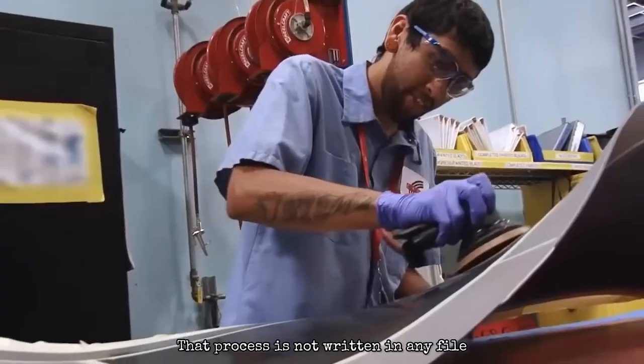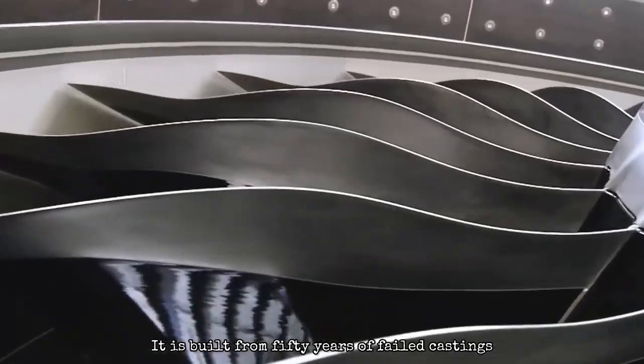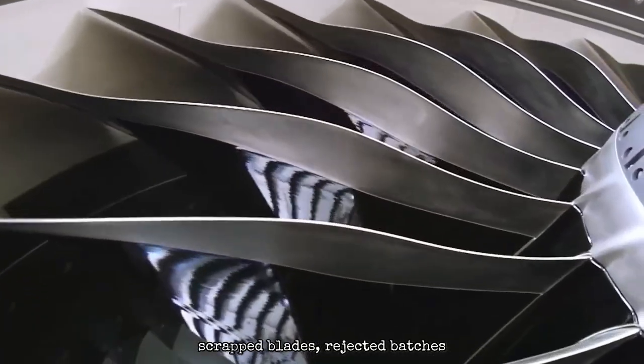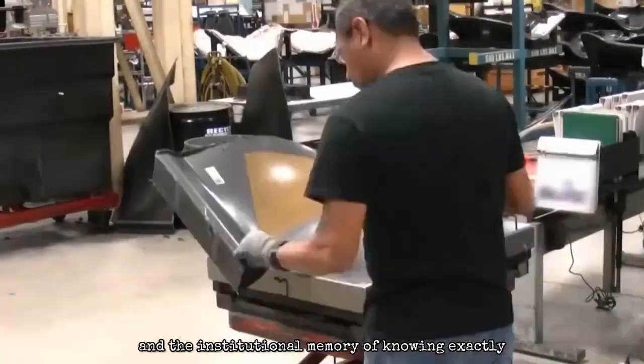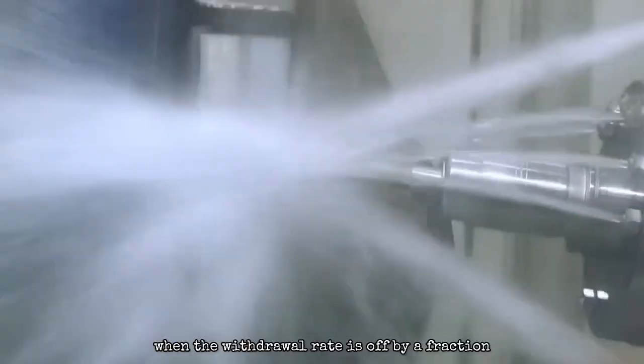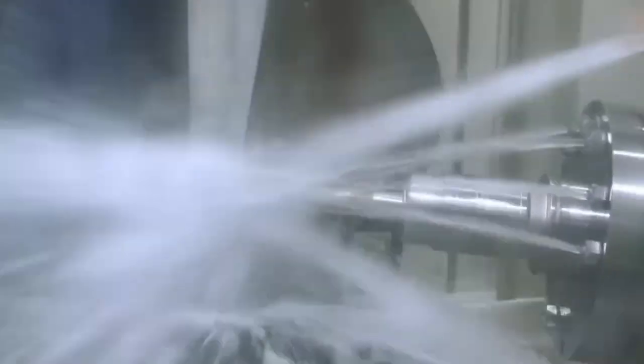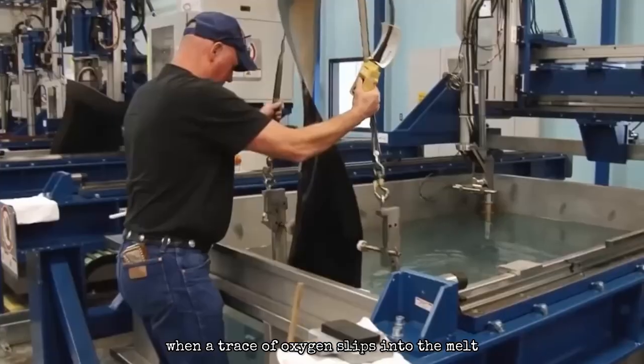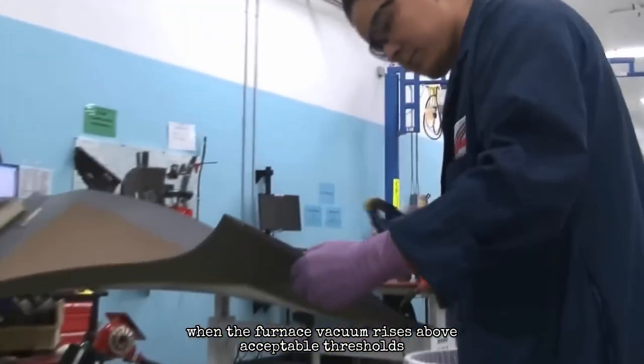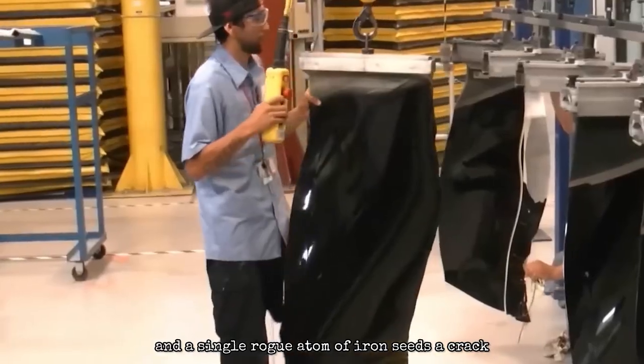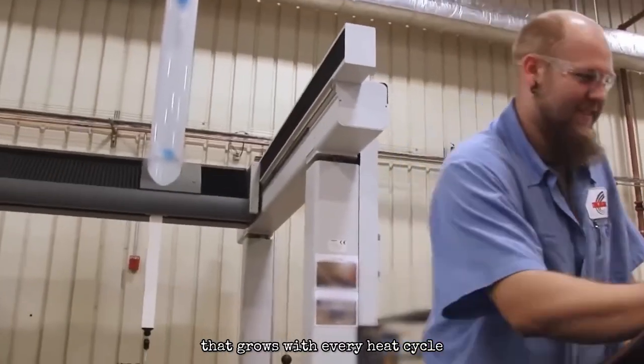That process is not written in any file. It is built from 50 years of failed castings, scrapped blades, rejected batches, and the institutional memory of knowing exactly what goes wrong when the withdrawal rate is off by a fraction of a millimeter, when a trace of oxygen slips into the melt, when the furnace vacuum rises above acceptable thresholds, and a single rogue atom of iron seeds a crack that grows with every heat cycle.